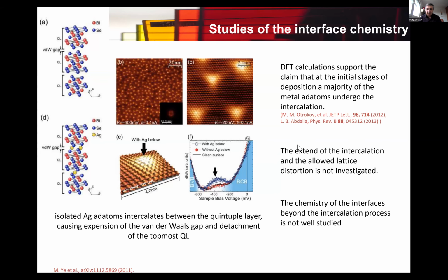So there would be some strain generated around this atom, and of course, this increases the free energy of the system. Okay, this is what we can understand, but there are no studies of what happens above this level of concentration of the metallic atoms. Where is this critical limit when the system cannot tolerate this extra strain anymore? So this is the area where our investigation started.